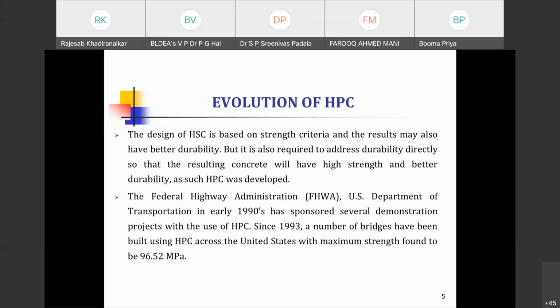Composition-wise, of course, there is a slight difference when you compare with conventional concrete. You have a lower water binder ratio in high performance concrete, and a large quantity of mineral admixtures or powder materials, and aggregates with good particle packing characteristics, because these things make a basic difference. And a high dosage of superplasticizer is a must, because if you need to maintain a lower water binder ratio or lower water content, then this higher dosage of superplasticizer is essential. These are some differences. The moment we start talking about HPC, we have to keep this basic difference in mind, and then go for the discussions.